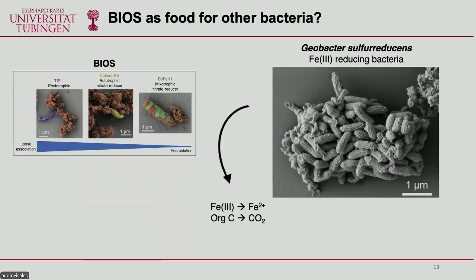And she, or we, I should say, are very interested in how all of these different biogenic iron oxyhydroxides can be used as food, essentially, for iron-reducing bacteria. This is a scanning electron microscopy image of the iron-reducing bacteria Geobacter sulfurreducens. And you see these ridges on their surfaces. This is very distinctive of Geobacter. And they can reduce iron 3 to iron 2. At the same time, they also degrade organic carbon to carbon dioxide.